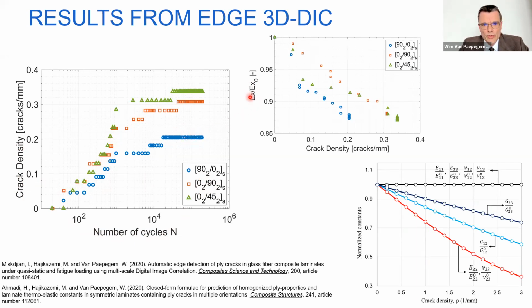You can also, because you have the stress strain curve in the actual direction as well, show the stiffness degradation versus the crack density. And then we are there because this is physics-based, a relation between the damage at micro scale and the stiffness, which is a structural macroscopic property. And we can do even more.